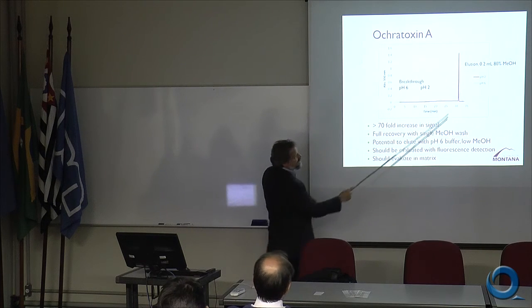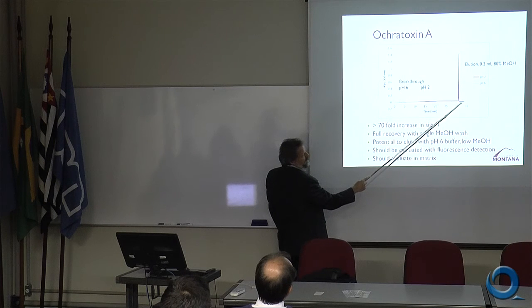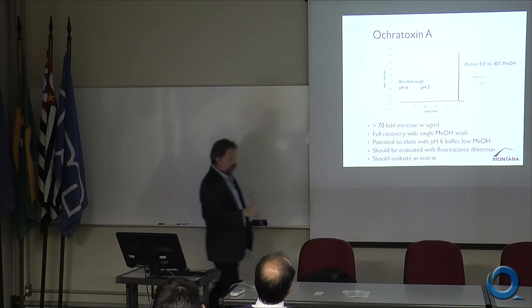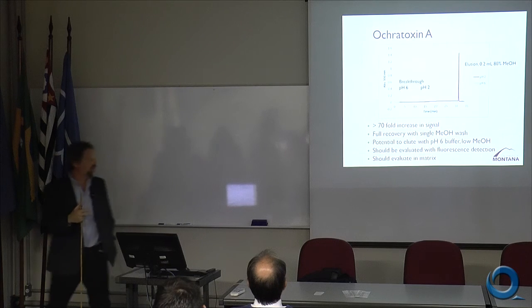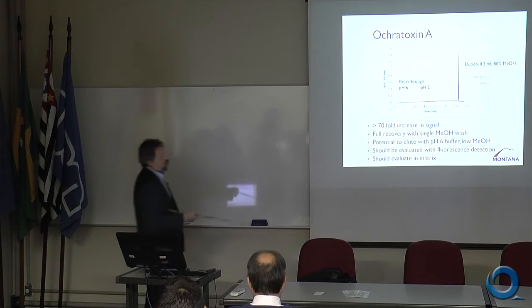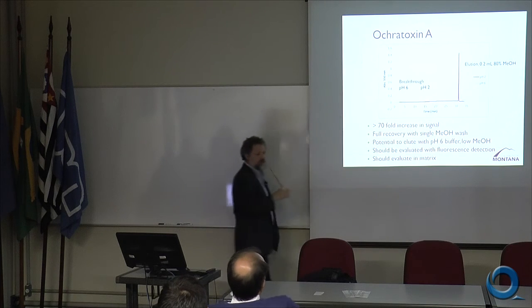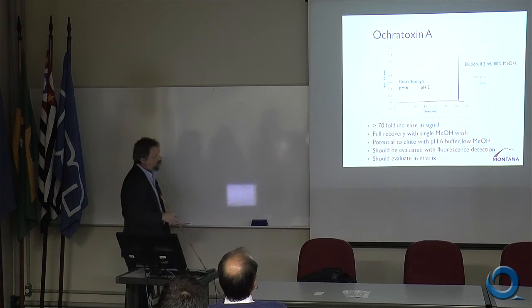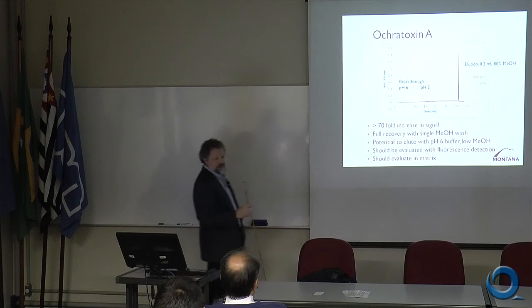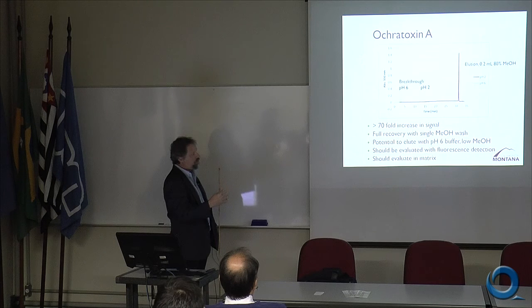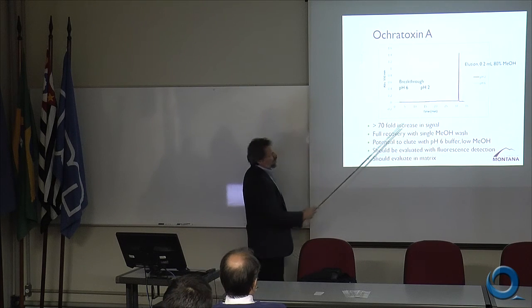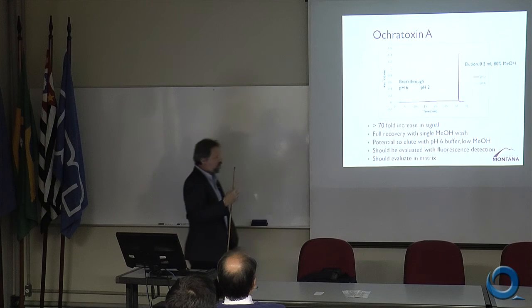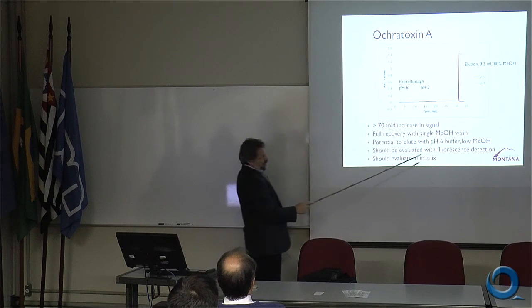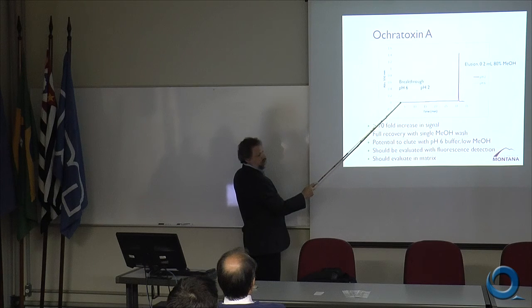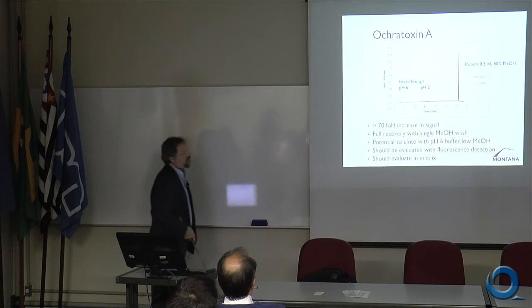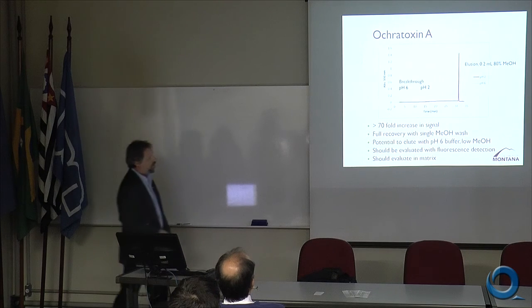And if we make a second injection of the 80% methanol, it shows up right here, this little blip. So we're getting essentially full recovery of that ochratoxin A using a single injection, and at the front of that injection, it's just being pushed right off the column by the 80% methanol. Now, the 80% methanol is not buffered, so it's probably at some intermediate pH. And so I expect that what we're seeing here is a combination of the methanol pushing the material off, but also the higher pH where that compound is really not retained, helping to desorb ochratoxin A from the nanoparticles.